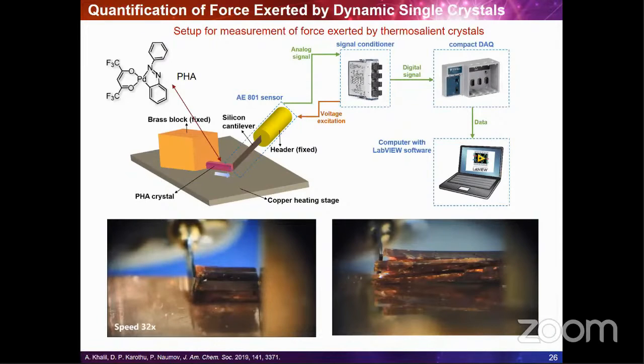In these measurements, we use small crystals, usually sub-millimeter to millimeter size, of one organometallic compound. You can see the structure here. And they were found to exert forces which range between 1 and 100 millinewtons upon expansion. If you calculate and translate this into power density, this comes to a volumetric power density of about 1 to 3 megawatts per cubic meter, and this is sufficient, comparable to the existing multi-component actuators.